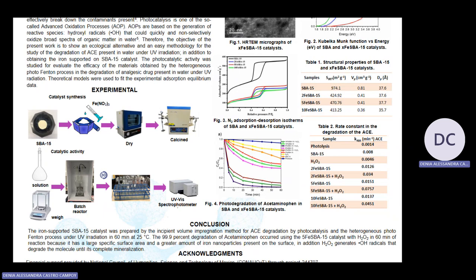For the catalytic UV test, a 20 ppm solution of acetaminophen is prepared and the catalyst is weighed. Both are added to the reactor to reach adsorption equilibrium. The solution is left for 30 minutes in the dark with controlled temperature. The mercury lamp is then turned on and liquid samples are taken at different times to be read on a UV-Vis spectrophotometer, to measure the concentration of the drug at different times.